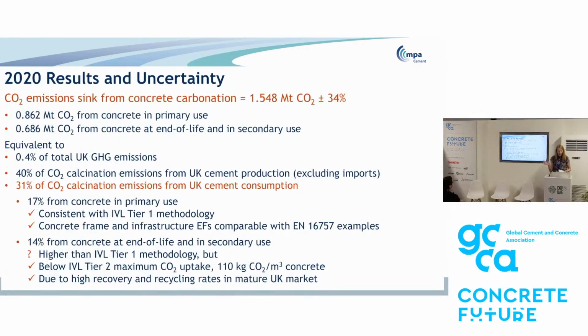So I haven't gone through all the uncertainty analysis, because that's probably a whole other 3-hour session on its own. But in terms of the results, we found that in 2020, the model came up with, for the UK, an emission factor of 1.548 million tonnes of CO2, plus or minus 34%, as the contribution of concrete as a sink in the UK for that single year. So that's equivalent to about 0.4% of UK greenhouse gas emissions and 31% of the calcination emissions from UK cement consumption.